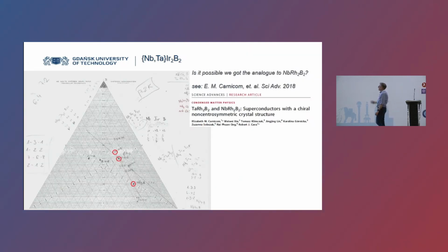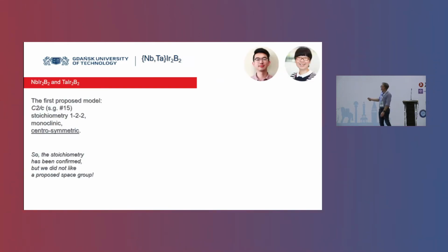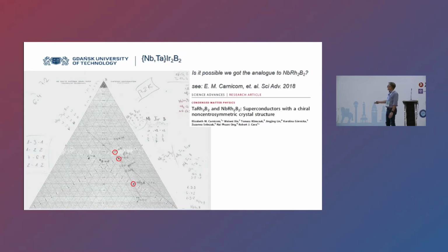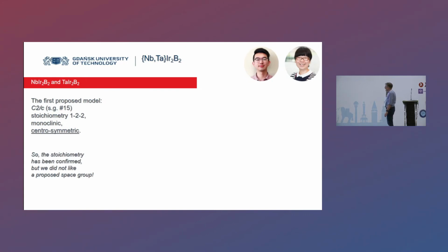And here is a first conclusion, or actually the first question. Do we have the same crystal structure which we observed for rhodium-based compounds, 1, 2, 2, niobium, rhodium, 2b2? That paper was published 4 years ago, and this is the chiral crystal structure, non-centrosymmetric, fine, the same composition as this sample, so we thought maybe it's the same crystal structure, but it appeared that it's not. From the very beginning, we knew it's not the same crystal structure, and without the help of Wei Xie and her student, we couldn't move to another level. Without the help of the crystallographers, we couldn't refine this crystal structure. So the first proposed model was C2 over C, which is the space group 15.